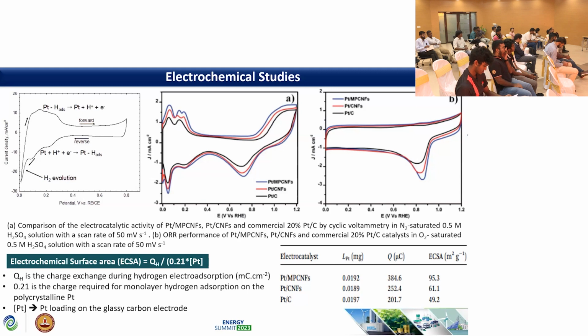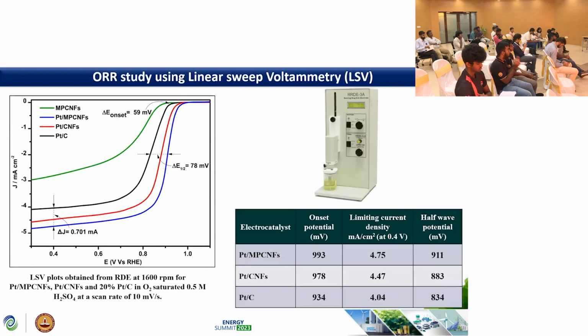And further we did the ORR performance of the materials and compared with the commercial PTC also in oxygen saturated sulfuric acid solution. We could see that the ORR performance has increased considerably compared to the commercial PTC. And we extended this study on ORR using linear sweep voltammetry with a rotating disc electrode at 1600 RPM. Eventually we can see that the onset potential and half-wave potential have shifted more positive in the case of mesoporous carbon nanofibers compared to commercial PTC.